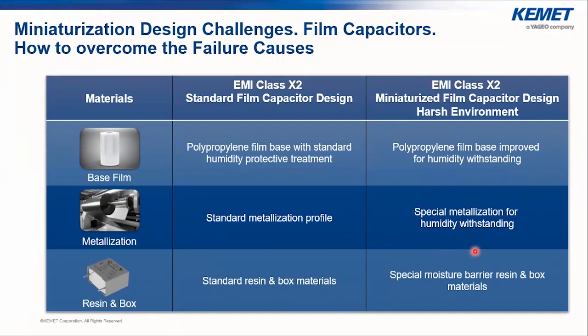The metallization resistance selection has an important role in the right compromise between safety aspects and capacitance stability. For the new designs, a special metallization for humidity withstanding has been used. There was also a mechanical challenge in manufacturing capacitors with smaller capacitance values. Lower capacitances require less film and less metallization material, making the product more susceptible to damage due to humidity. So for the new miniaturized designs, a special moisture barrier resin and also special box materials have been used.